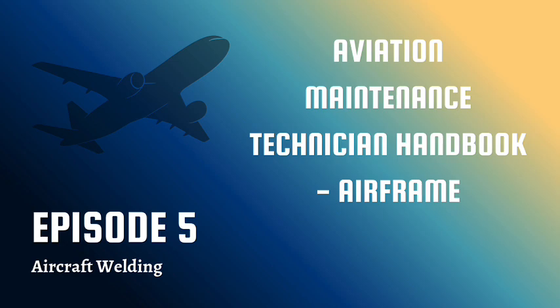However, metals like aluminum and magnesium have a major problem. They instantly form a very tough, refractory oxide layer on their surface when exposed to air. Think of aluminum oxide or magnesium oxide. These oxides have melting points far, far higher than the base metal itself. So if you don't get rid of that oxide layer first, you can't actually fuse the metal underneath. The oxide acts like a barrier. Exactly. You'll just melt the metal under the oxide skin, but you won't get a true fusion weld. The oxide inclusions will make the weld incredibly weak and brittle.